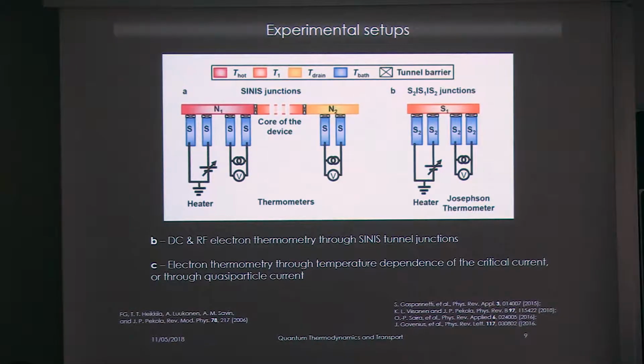Okay, so let's go a little bit to show how we typically proceed in terms of experiments. As I was saying, the observable on which we are concentrated is the temperature, okay, because we cannot measure heat currents in a solid-state system. There is no ammeter for heat currents like there is an ammeter for electric currents. So what we typically do is to measure the electronic temperature of a reservoir, and the basic assumption is that we can define the temperature in the system, okay? To define the temperature, we need the electron-electron interaction to be sufficiently strong to thermalize the quasi-particles among themselves. And typically, the temperature of the lattice is sufficiently low that the electron-phonon coupling is weak. So we can create in the system a sort of quasi-equilibrium regime.